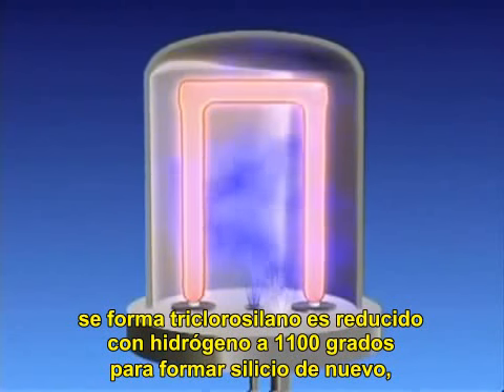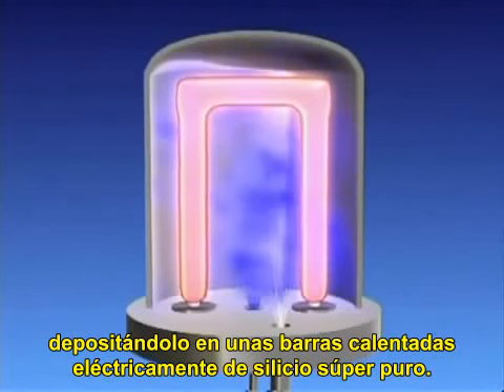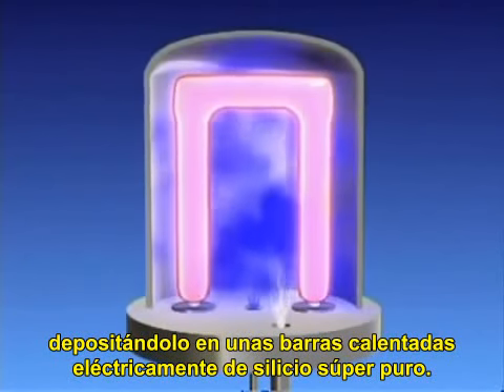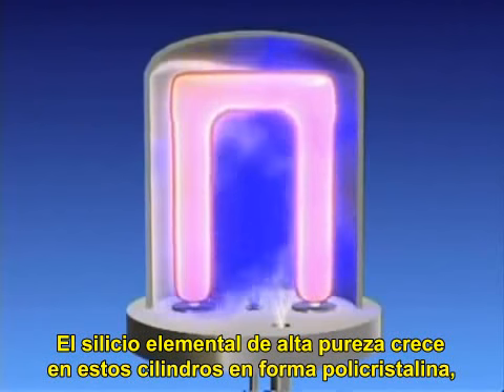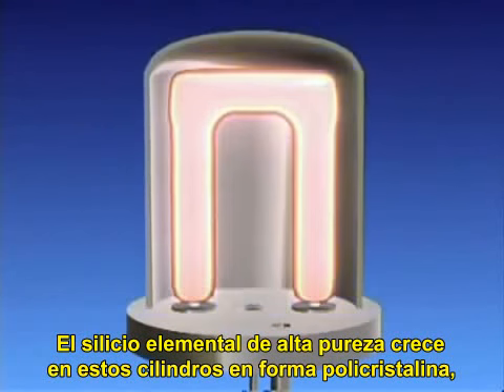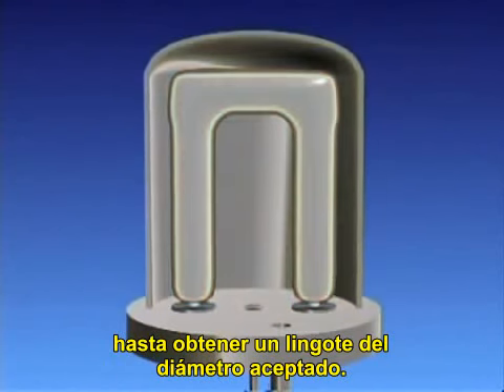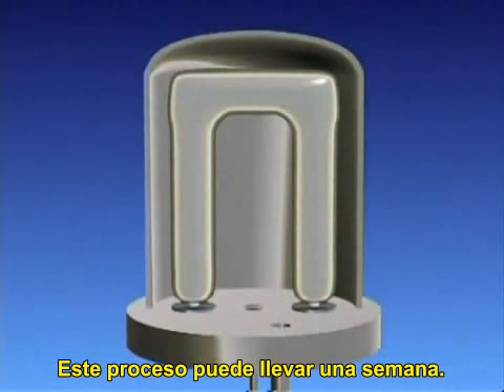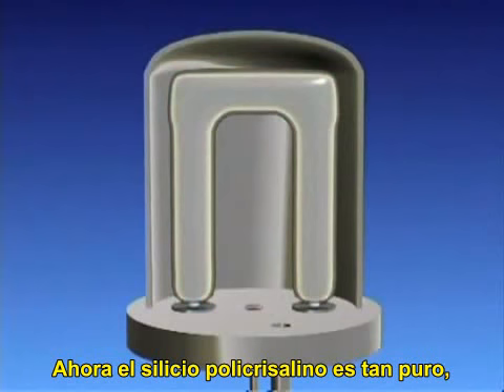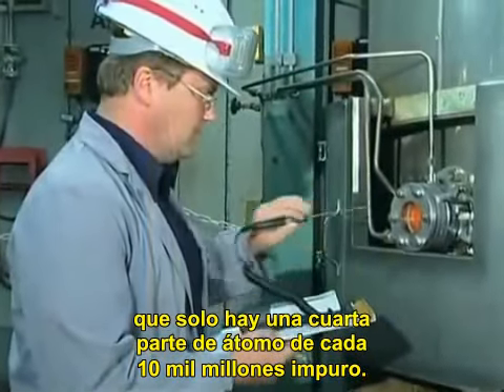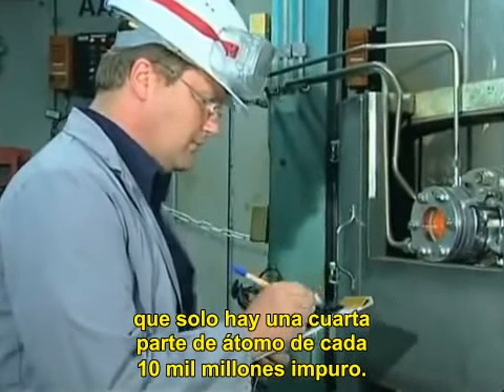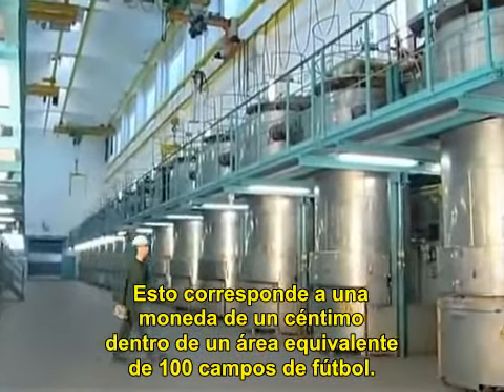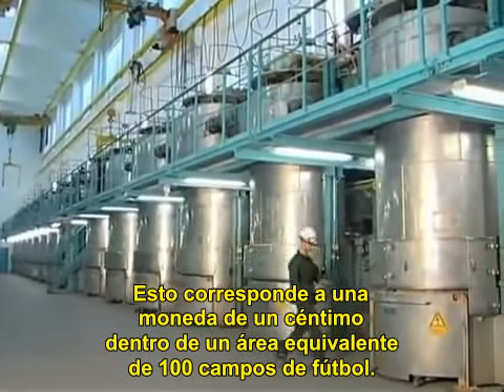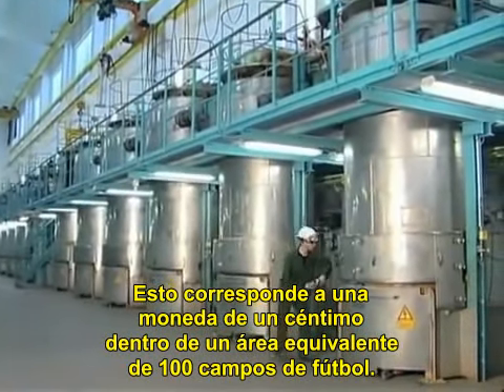centigrade to form silicon again, which is deposited on electrically heated hyperpure silicon rods. Hyperpure elemental silicon grows on the rods in polycrystalline form until an ingot of specified diameter is obtained. This process takes roughly 1 week. The polycrystalline silicon, in short, polysilicon, is now so pure that there is only 1 foreign atom per 10 billion silicon atoms. That corresponds to a 1-cent coin on an area equivalent to 100 football fields.